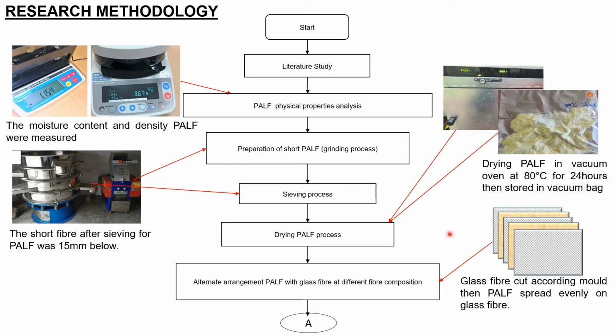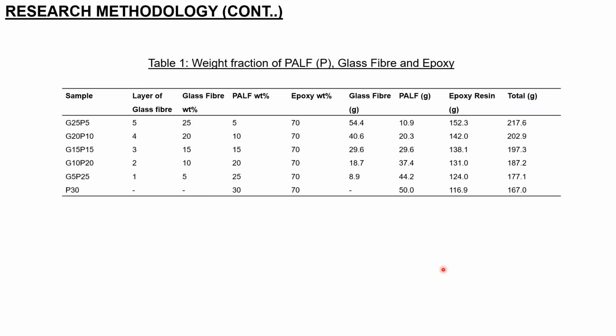After that, we dry the PALF in an oven at 80 degrees Celsius for 24 hours, then store it in a vacuum bag. After that, we alternately arrange PALF with glass fiber at different fiber compositions. Glass fiber is cut accordingly in the mold, then PALF is spread evenly on the glass fiber.